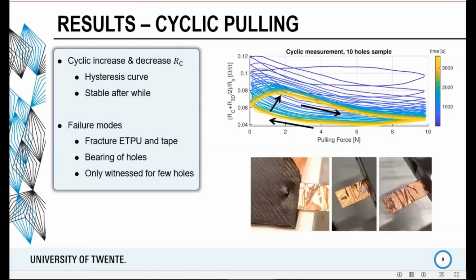And for the fracture, the main failure mode was a breakage of the TPU. But we could also see, for the low number of holes, the bearing of the holes. You could really see that the holes were tearing and elongating in the pulling direction. So in that case, multiple holes help because you really distribute the stresses over the entire contact.